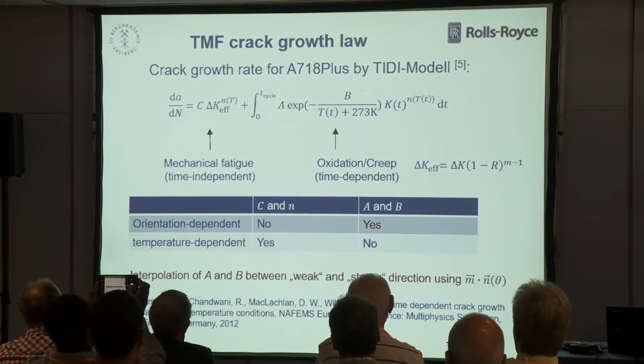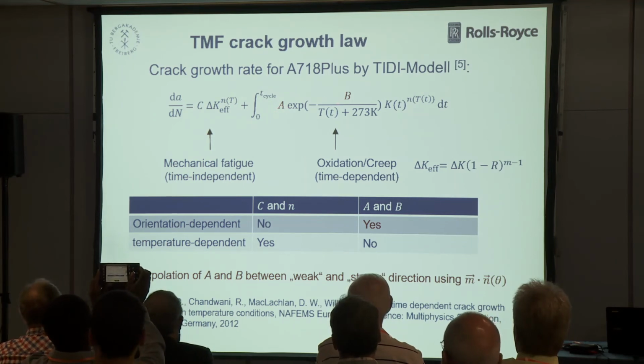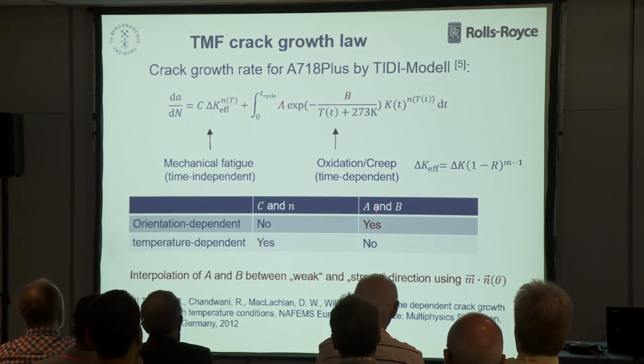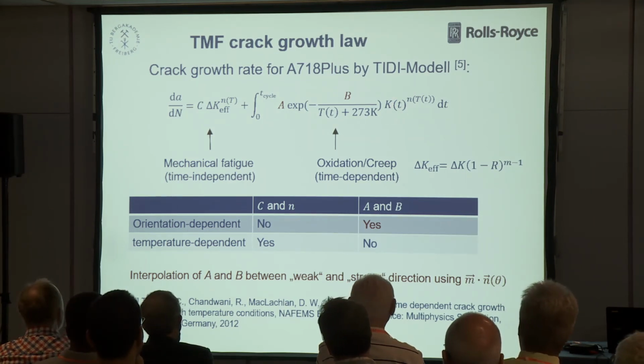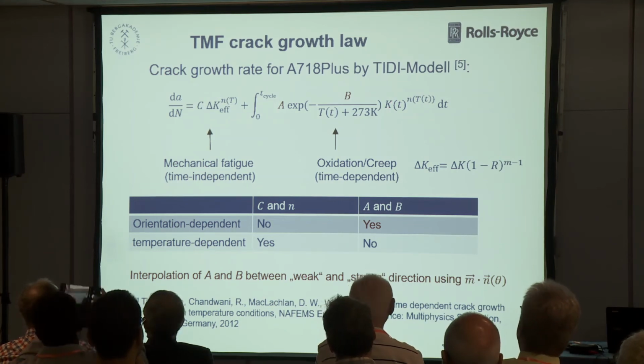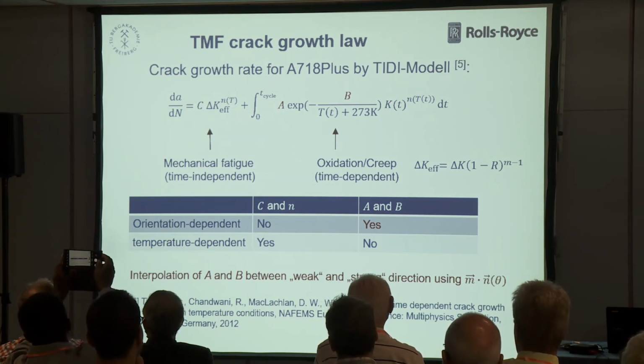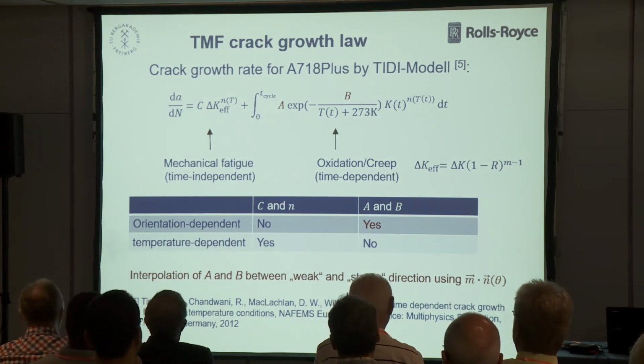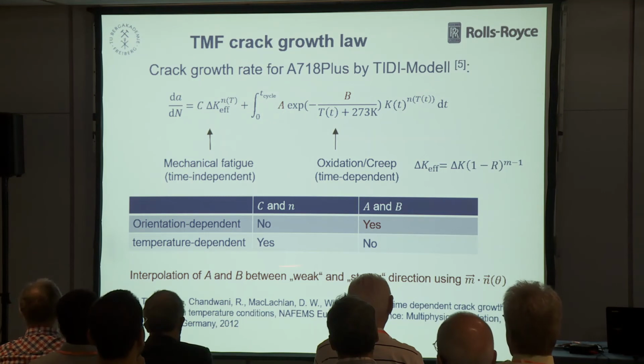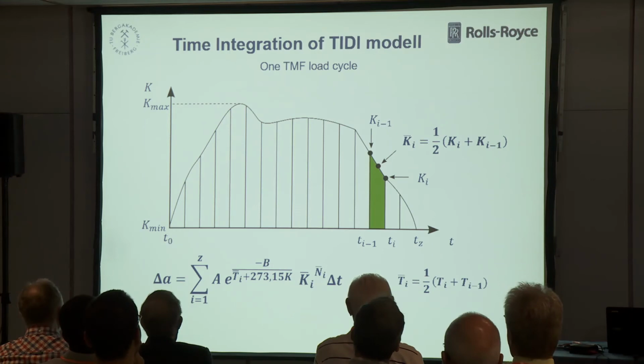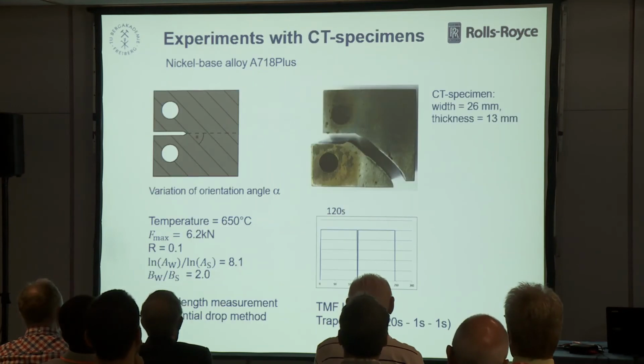And these two coefficients, A and B, they are orientation dependent. Yeah? And temperature dependence is introduced here and here. And you see the loading is described by the absolute value of the K factor. So we consider here small scale creeping. Creeping is controlled by the K factor, the small creep zone. And for these parameters, we also need to interpolate along the different directions. This second integral has to be integrated. I skip it. This is a numeric thing.